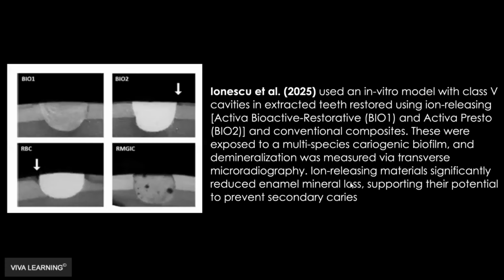So here are some studies to show, first of all, that the material can prevent demineralization of surrounding tooth structure. This study used an in vitro model with class 5 cavities. Basically, they got extracted teeth and made little class 5s in them, so little boxes. They put the Activa material, a conventional composite, and also RMGI into those little boxes. Then they were exposed to a multi-species cariogenic biofilm. So they try to grow caries by putting these teeth in an environment with some bad bacteria, and then they cause demineralization. The amount of demineralization at the margins of the fillings was measured using transverse microradiography, so looking at mineral content loss through x-rays, essentially. What they showed, what you can see in the pictures, is the ion-releasing material significantly reduced enamel mineral loss, supporting the potential to prevent secondary caries.